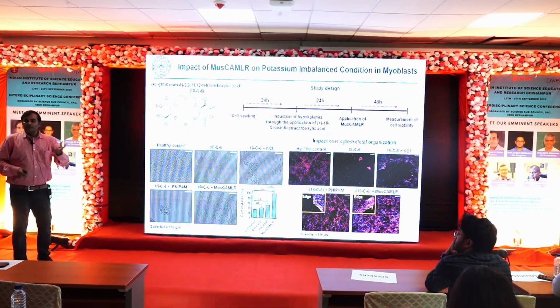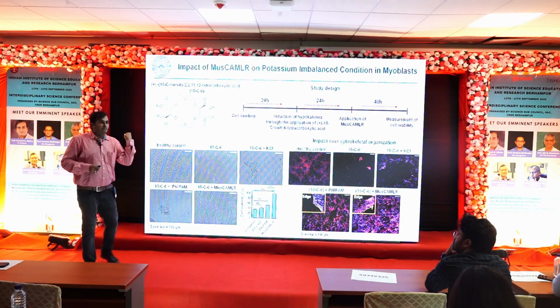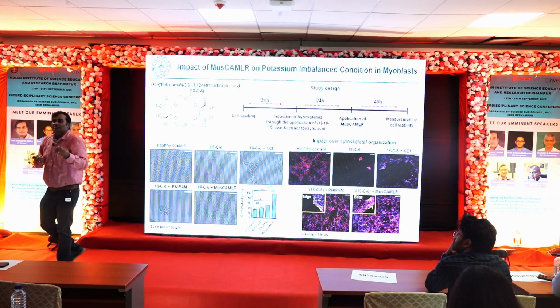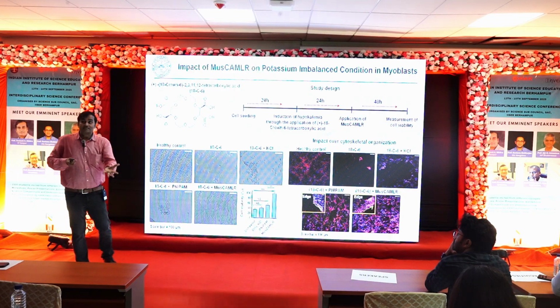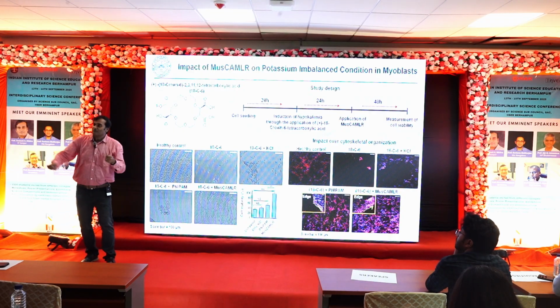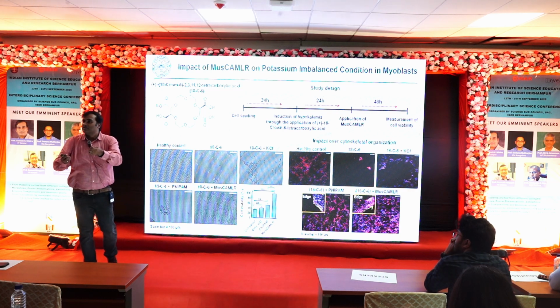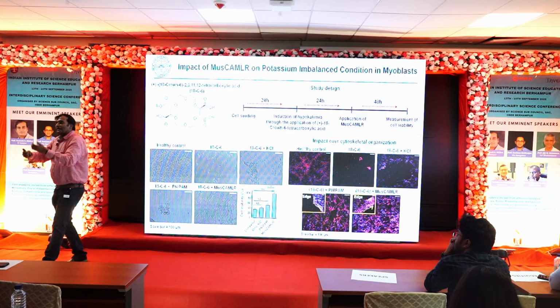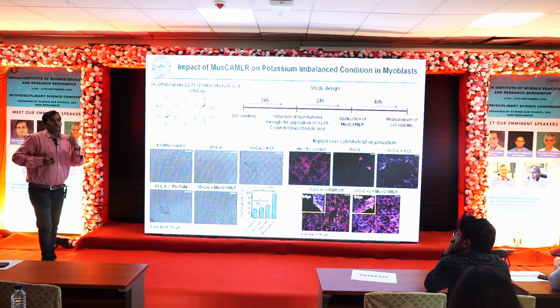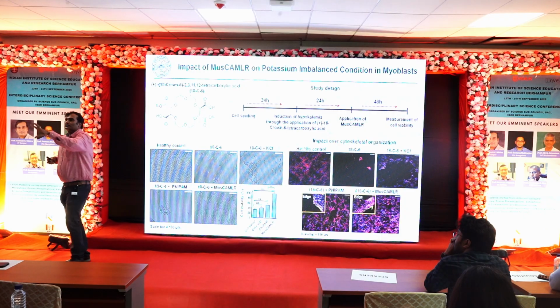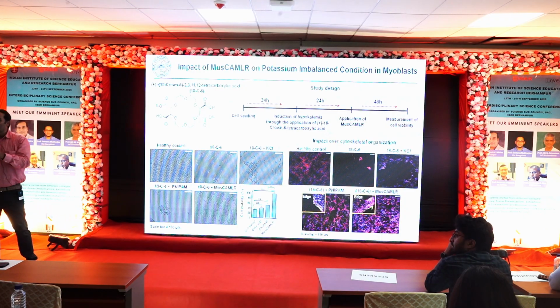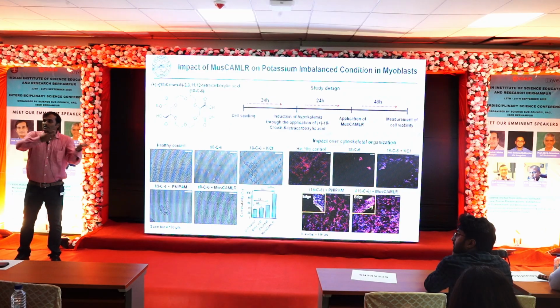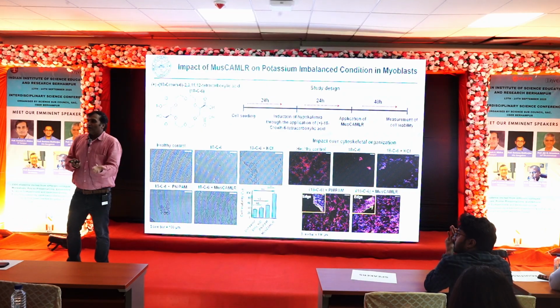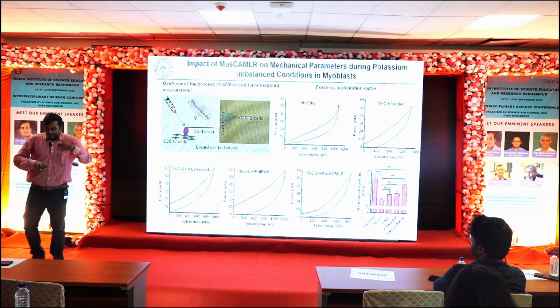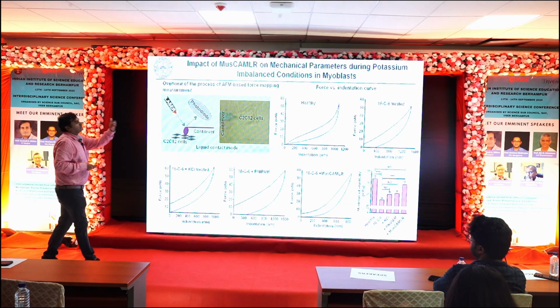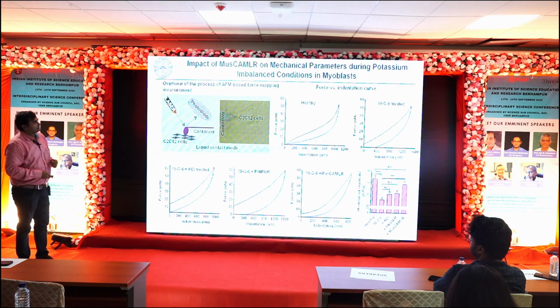Then we used crown ether to extract all the potassium ions from the system, and we tried to see what is happening in that manipulated system, and we saw that all the cells started detaching from the surface. Then we added our MusCaMLR and we saw that attachment starts again. This is called a negative way of doing things. Suppose you do not know that a particular gene is responsible for a function. So what do you do? Either you knock it out or you knock it down, and then you see what kind of effect it has. On attachment property using AFM, again we got that it is actually enhancing the attachment and the mechanical property.